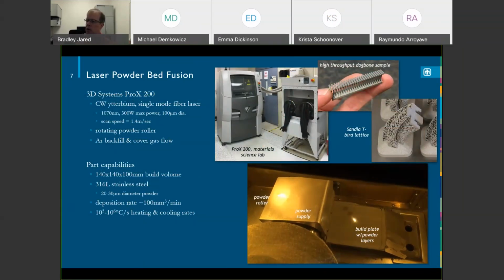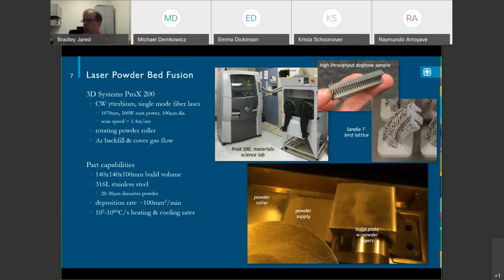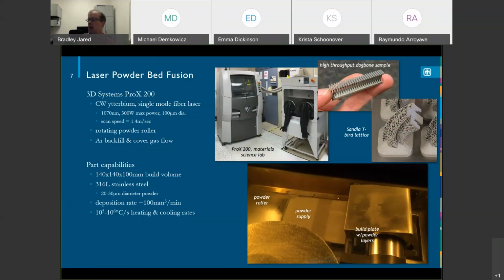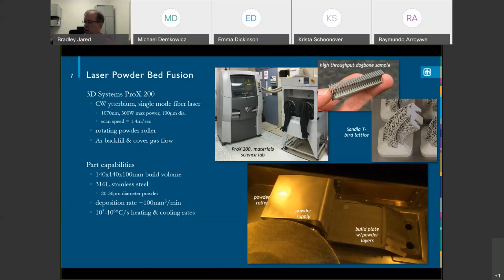We run at about a micron wavelength. Max power is 300 watts. We typically run about 100 to 110, and then we have about a 100 micron spot size. So in this process, you put down a 30 micron layer of powder. On the bottom right, you see the video of the actual machine running. Then we scan a laser at a high speed, about 1.5 meters per second.